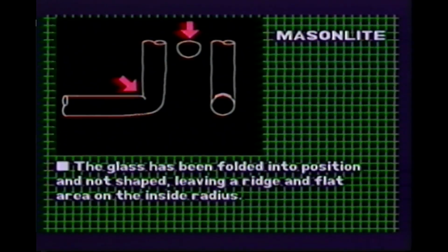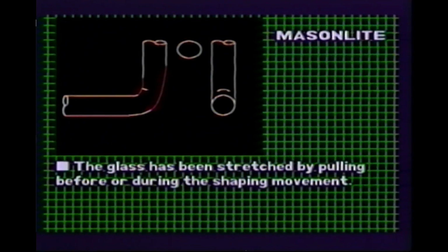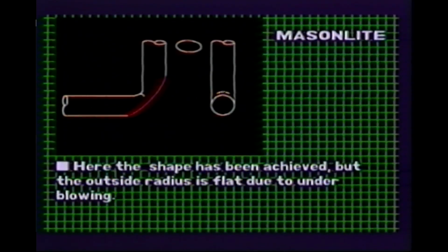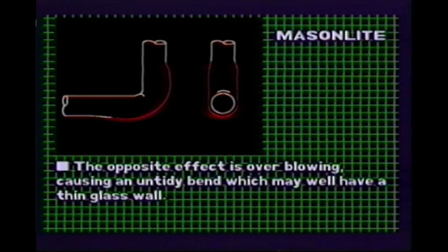The following are examples of the more common mistakes made when forming the right angle bend. The glass has been folded into position and not shaped, leaving a ridge and flat area on the inside radius. The glass has been stretched by pulling before or during the shaping movement. Here, the shape has been achieved, but the outside radius is flat due to underblowing. The opposite effect is overblowing, causing an untidy bend, which may well have a thin glass wall.